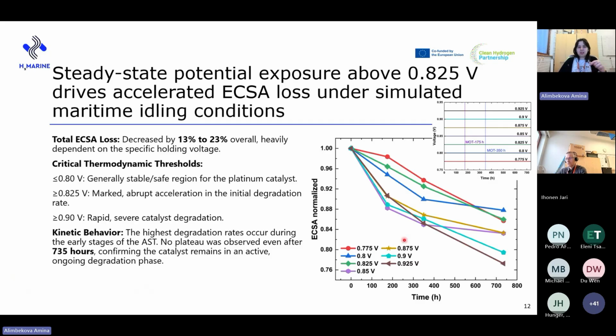As we established, the steady state voltage holds within the electrochemical window between 925 and 775 millivolts is designed to mimic these maritime idling conditions. In the literature, PEM fuel cell operations below 0.8 volts is considered safe for a platinum catalyst, but operation above 0.9 volts is known to trigger catalyst degradation. Our platform, the testing setup, allowed us to map the influence of this holding voltage on the degradation by running all these tests simultaneously.